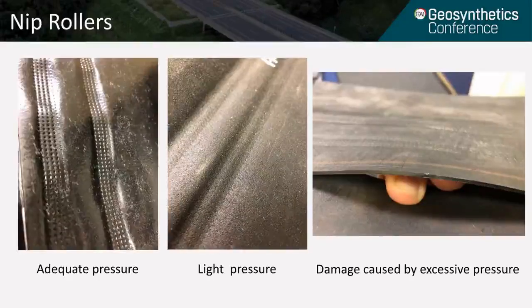Evaluating the impressions left by the nip rollers on a completed seam can be key to identifying problems. The photo on the left shows adequate pressure. The photo in the center shows light pressure, which is going to be an issue. And there's an obvious issue with the photo on the right where the pressure is cutting through the liner, so it's way too much pressure.